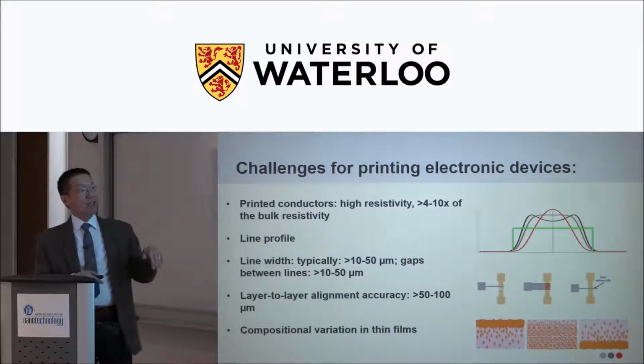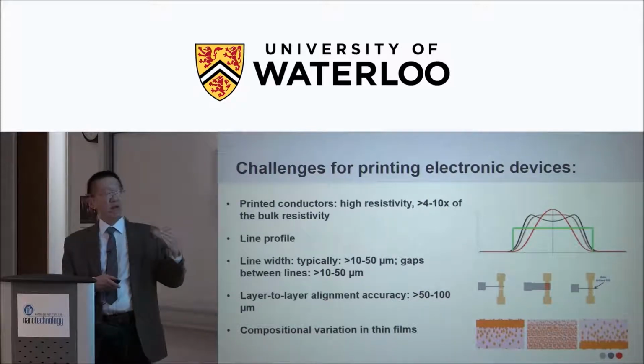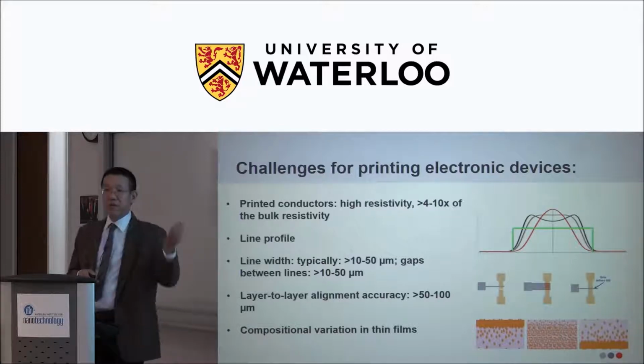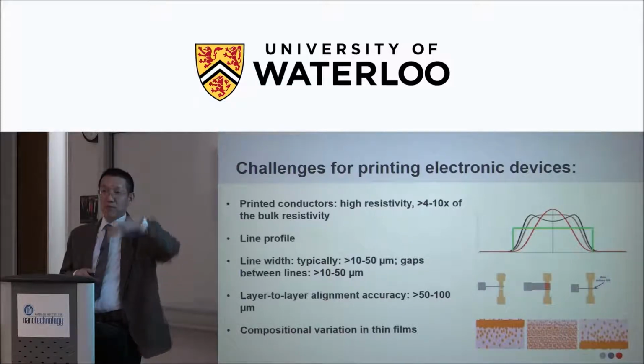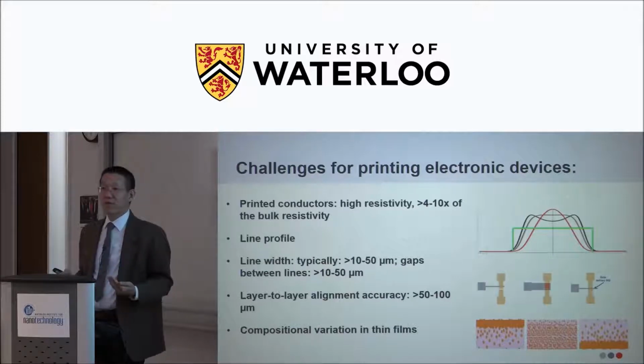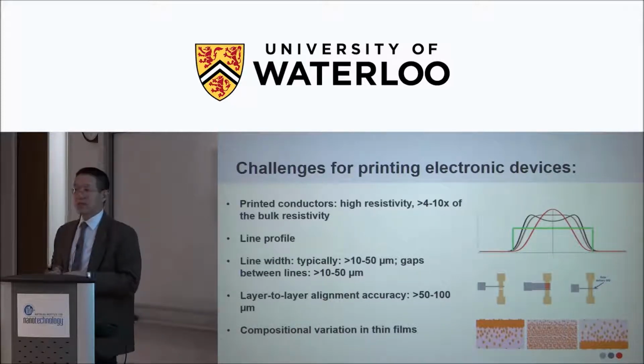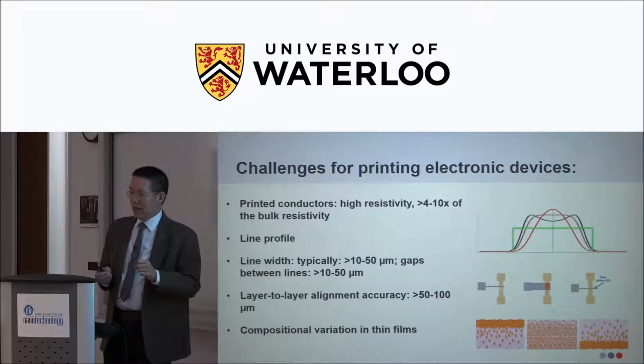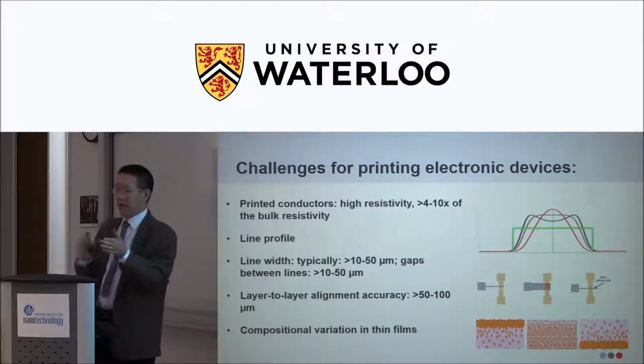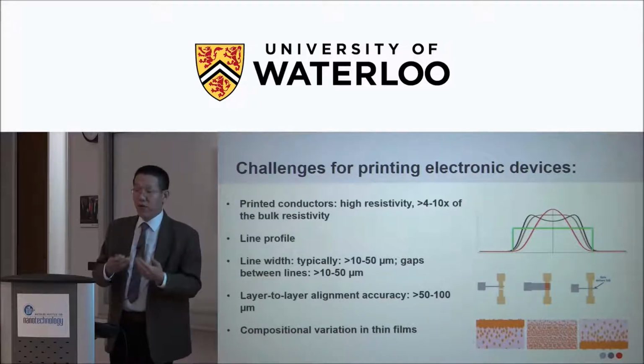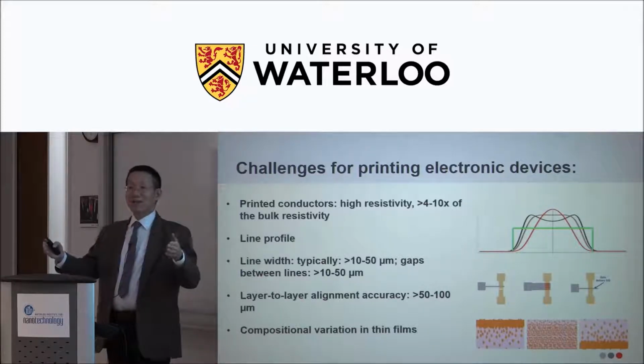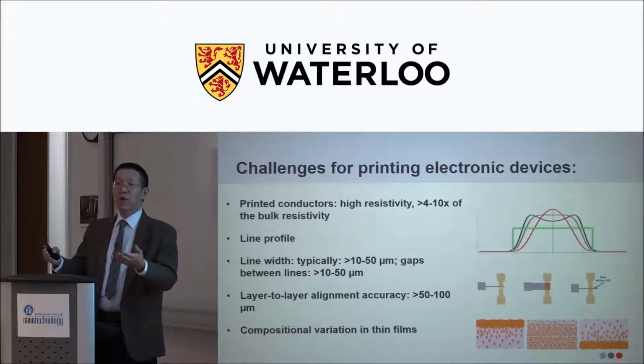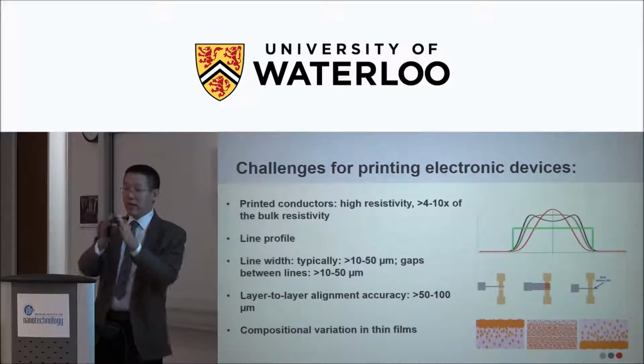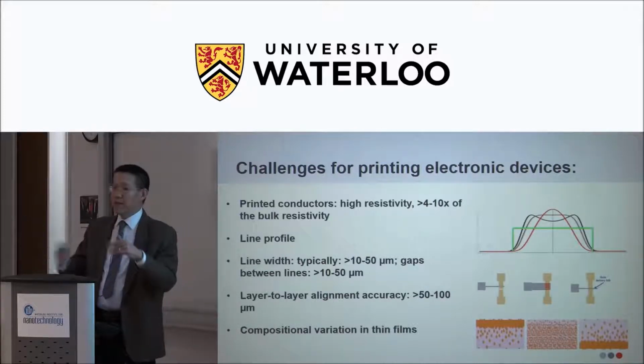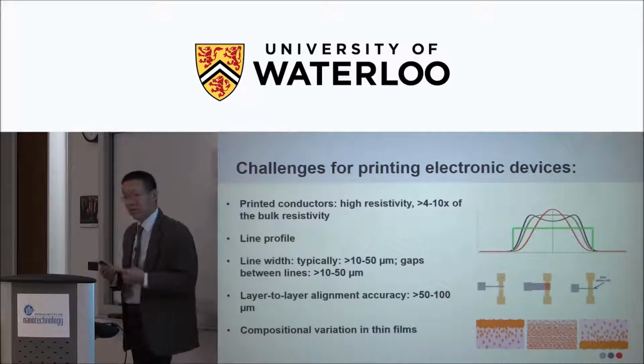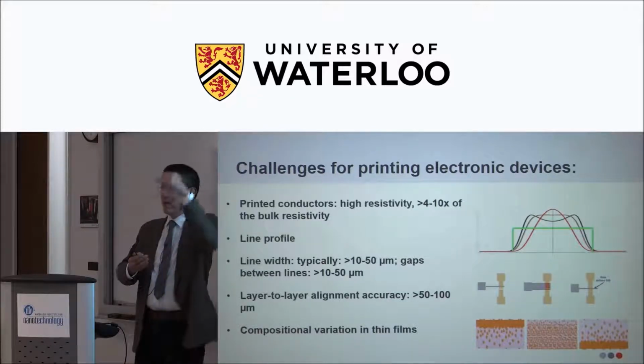And then another thing is the compositional variation in thin films. When you print, when it dries up, the composition will vary from the top to the bottom, depending on the composition of the film. One typical example is printed metal ink. You say, okay, I have very high conductivity ink, but those inks were formulated for lateral conduction, like for printing your microwave oven control panel. What they care about is from A to B. But if you want to use that ink to make your transistor, you are talking about vertical conductance.